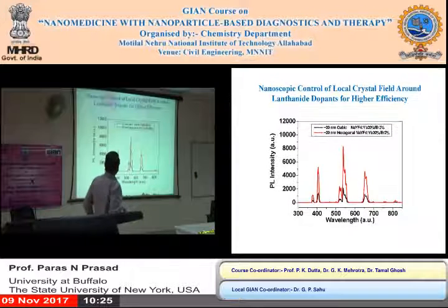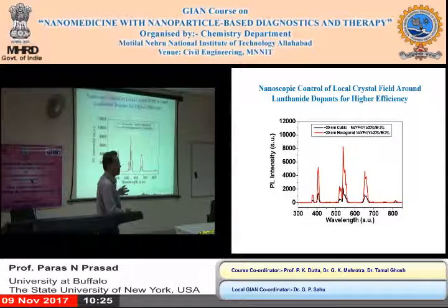So that's the designation. They are 20 nanometer, but they can be in 2 different crystalline phases, cubic or hexagonal. The cubic, being very symmetric, has very small upconversion. But when you go to hexagonal, the upconversion at many wavelengths is very strong.